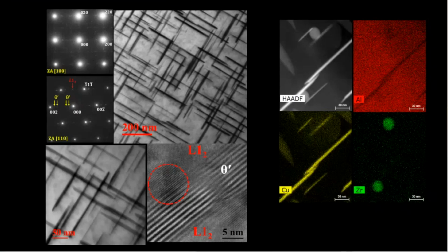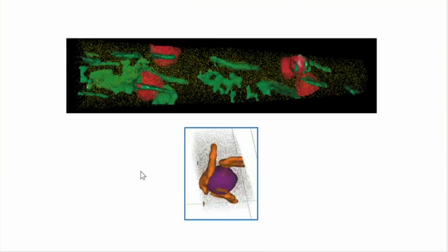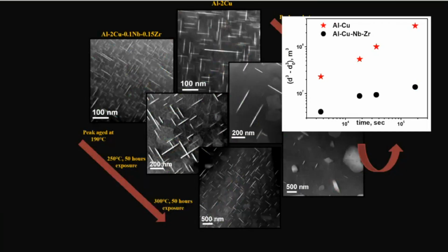Therefore, we can inherit the distribution of the ordered precipitate at high temperature to have a similar distribution at lower temperature aging, because every plate has nucleated on these ordered precipitates. Every theta prime and theta double prime precipitate has nucleated on this. Therefore, you get a very fine distribution. Unfortunately, I don't think I can show you the 3D, but you can see that there's a plate. Below, you can see that all the variants of theta double prime and theta prime nucleate on the pre-existing L12 precipitates. So this is the microstructure evolution you see.